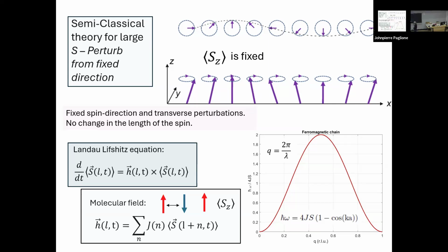So if you have an exchange interaction that couples these spins, that ties them together, the molecular field that acts on one of these is simply given by this formula here. It's the exchange interaction times the magnetic moment of the neighboring spins. Now, you can solve this equation to first order using perturbation, where you assume that the molecular field is constant for all the spins, and then you can set up a series of first order equations and basically crank through the linear algebra, and you're done.